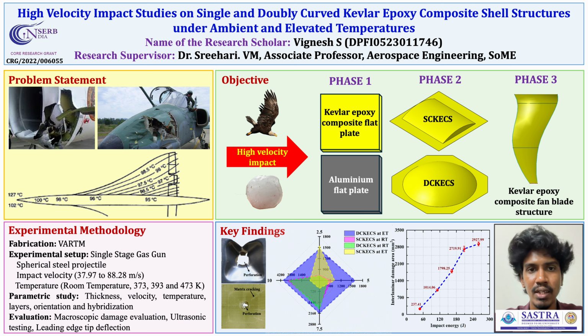After impacting, we also investigated the macroscopic damage in the composite laminates, and through thickness damage evaluation was done using ultrasonic testing. We also measured the leading edge tip deflection of the gas turbine composite fan blades.